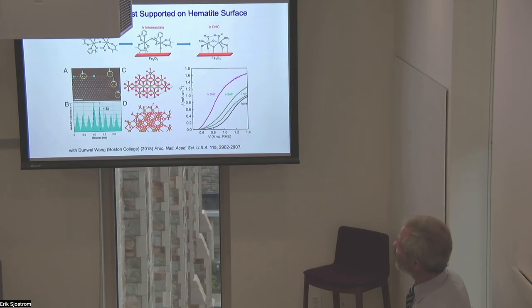And with Dunwei Wang, it was possible to image the surface of the hematite, and we can see these spots of higher density. This is sort of standing along between these two stars. And what we see is these two iridium atoms next to each other, only dimers. So the dimer bond on the surface remains as a dimer. There's no breaking apart, no forming of nanoparticles or anything.